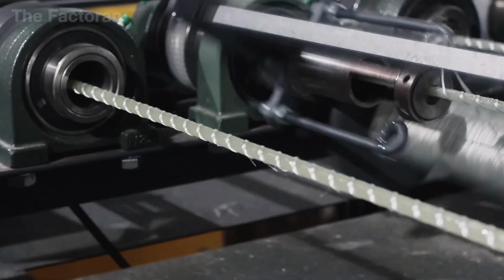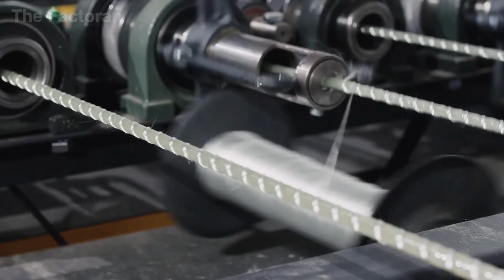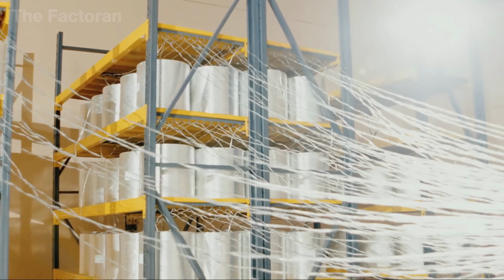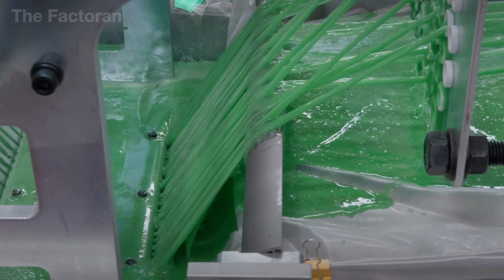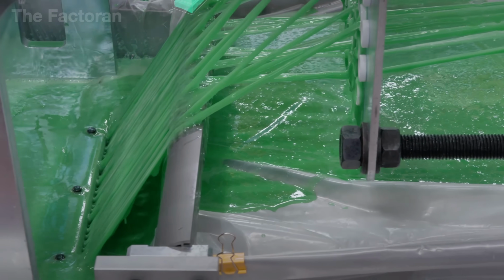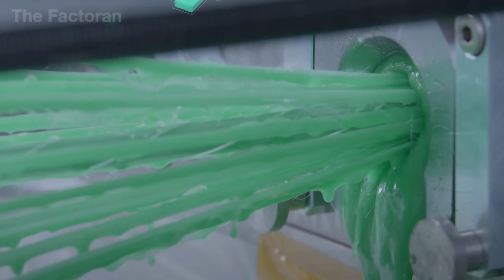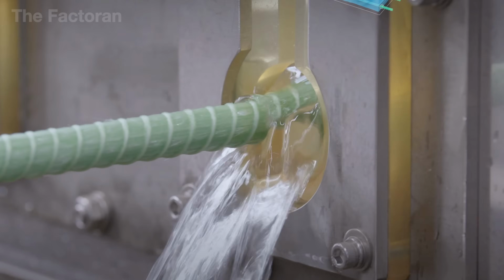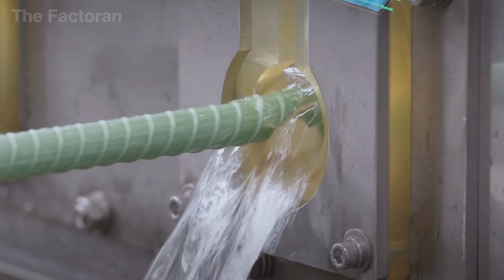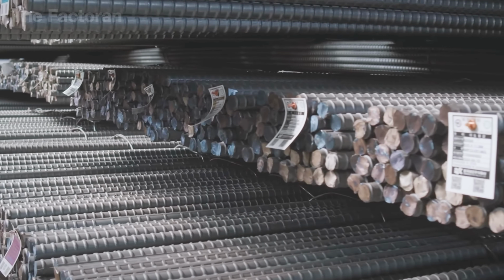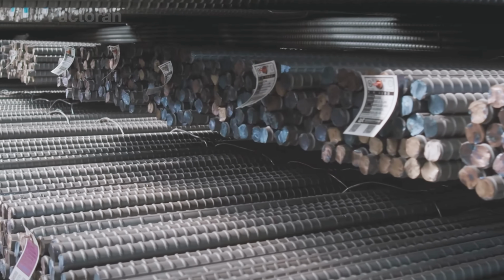Fiberglass rebar is actually made from two main components: glass fibers drawn from silica sand and epoxy polymer resin that binds and reinforces them. This combination creates a material that doesn't rust and can sit in seawater for up to 50 years without losing strength, while regular steel can start corroding after just a few months.